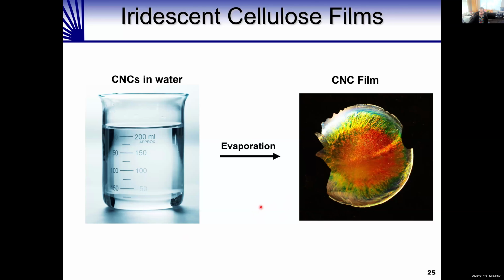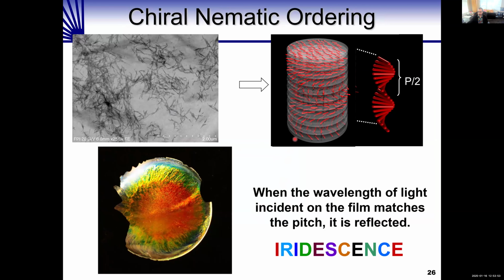I want to illustrate what this looks like. Imagine these rods, the cellulose nanocrystals, tend to align into layers as they dry. In the first layer, all the cellulose nanocrystals are aligned parallel to one another. In the next layer, they're also aligned parallel, but twisted a little bit relative to the first layer. The third layer, they're aligned but twisted a little farther. So what you build up in a film of cellulose nanocrystals is a series of layers whose orientation rotates through the film.